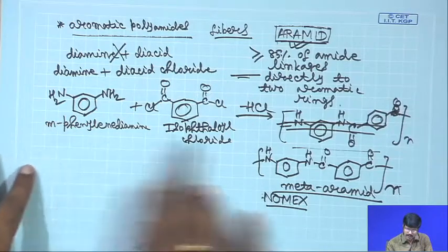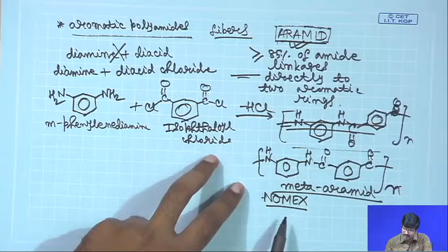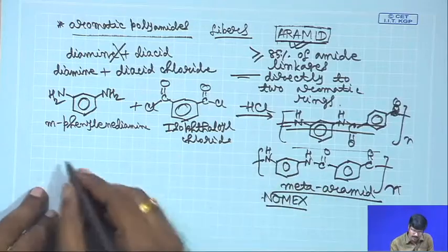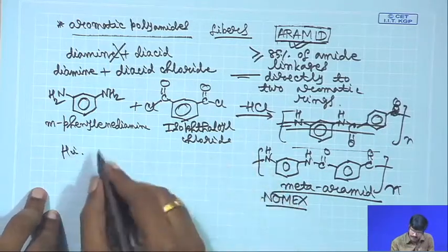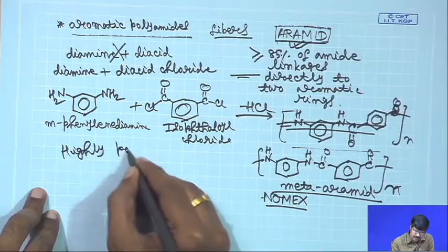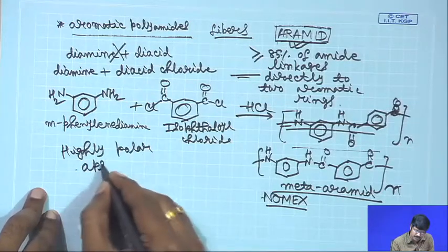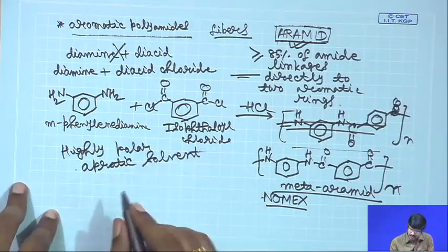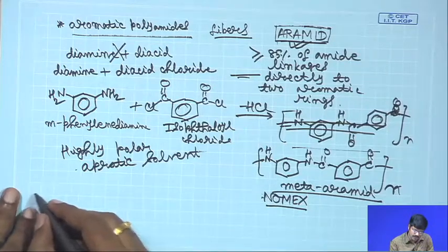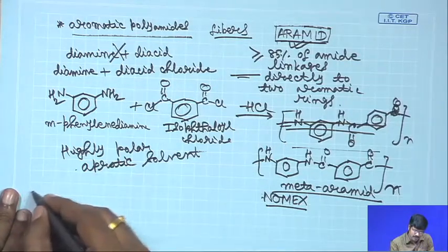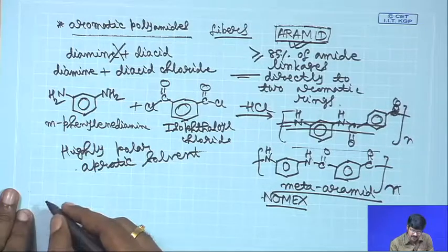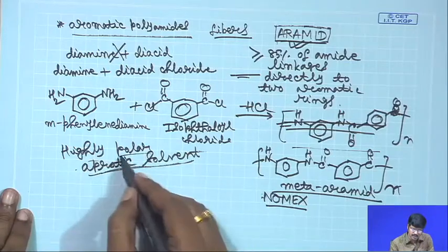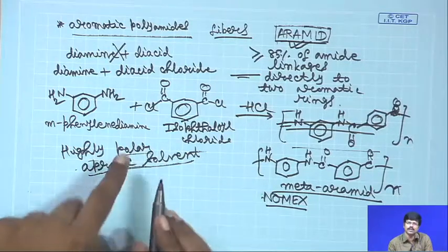And the polymerizations, these polymerizations are typically carried out in solution, and the solvent that you are using is a highly polar solvent, but this is aprotic solvent also. Unlike water, water can donate protons. Polar aprotic solvents you are going to use here. Say for example, just an example, DMSO, dimethyl sulfoxide, is a polar aprotic solvent that you are not going to use here, but in general polar aprotic solvents are solvents which are polar, but which do not have the ability to donate protons.